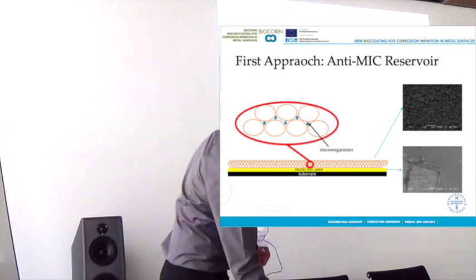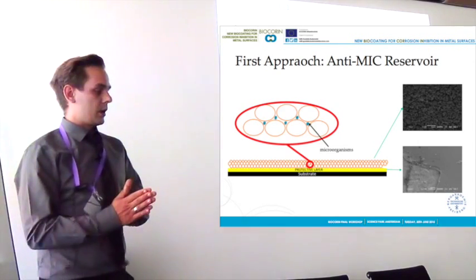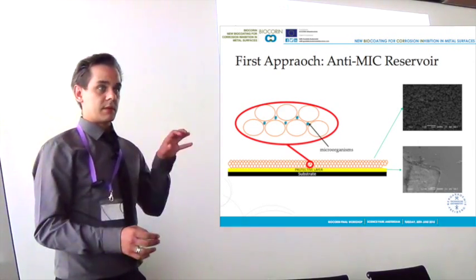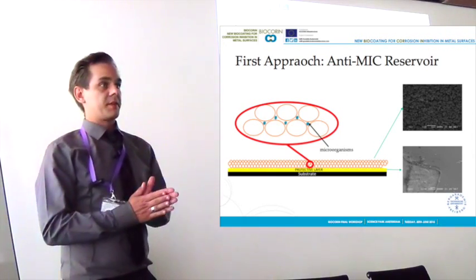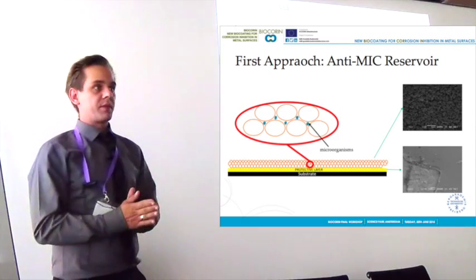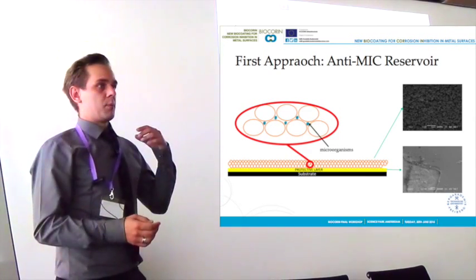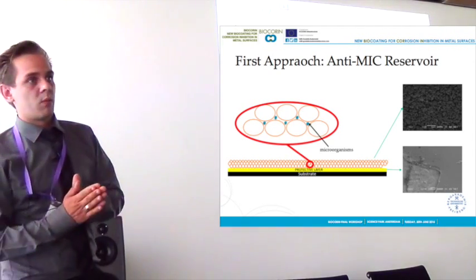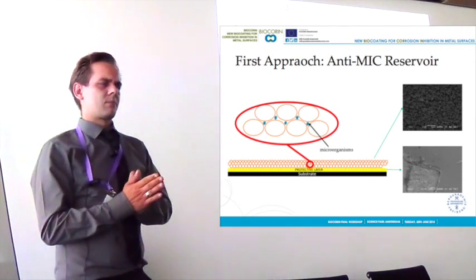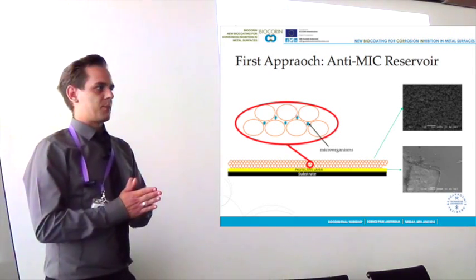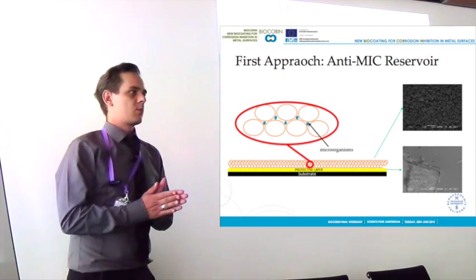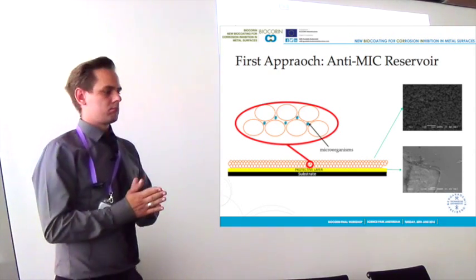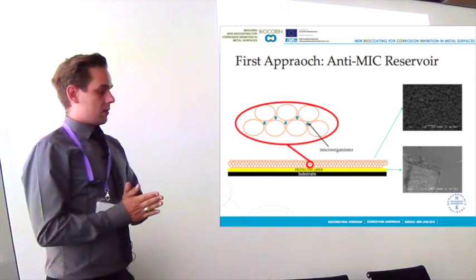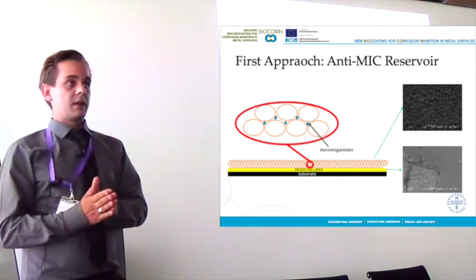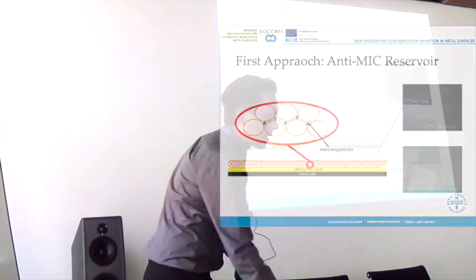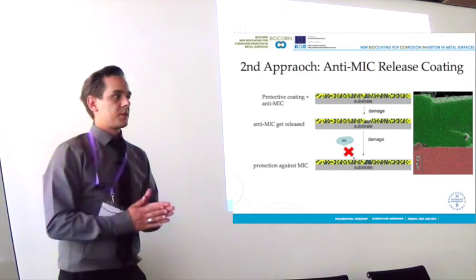Here you see the porous coating. We checked the viability of the microorganisms in the coating, and we found that they survive both the process and a long time in the coating. But a major disadvantage of this system was the application. This was, well, not that easy, and especially for the industrial process, it was not upscalable from the coating technique. So we stopped this and went to the second approach.